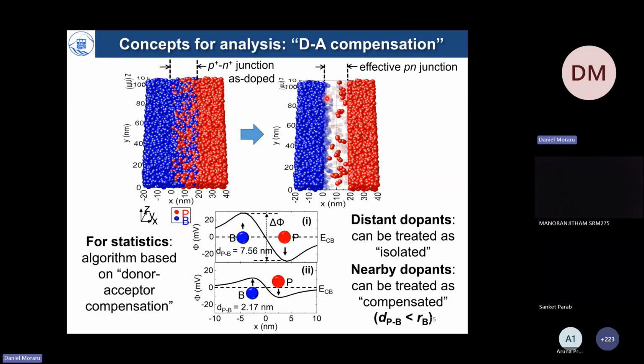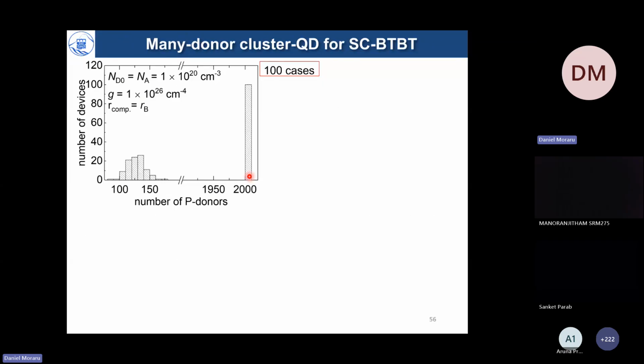And now we can see these clusters arranged in a few places. Because we have larger donor concentration, we also have donor clusters more visible in this depletion layer. So we counted statistically 100 cases. This is a little bit complicated statistics. The number of phosphorus donors is actually 2,000 in this nanoscale depletion layer. But then we can compensate, and after compensation, we are left with just about 100, 150 donors which matter.